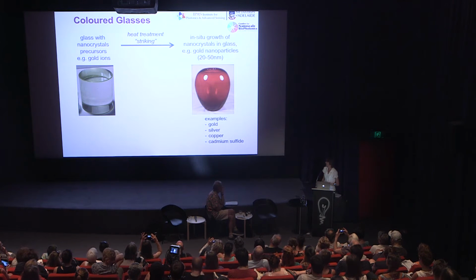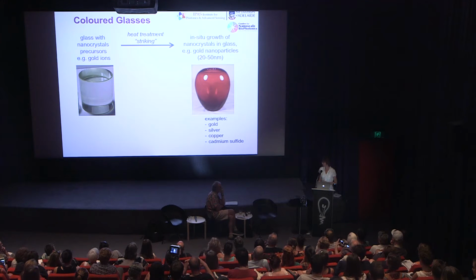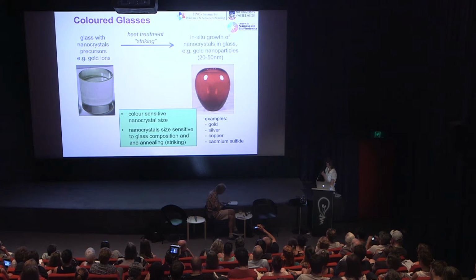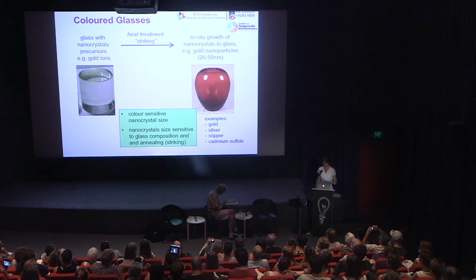And there are many other nanoparticles in glass that cause different colors. Other ingredients are silver nanoparticles, copper nanoparticles, cadmium sulfide, cadmium selenide. What really makes these colors so interesting is that the color is sensitive to the nanocrystal size. Depending on whether you have 20 nanometer or 50 nanometer nanoparticles in the glass, a different color is obtained. And which nanocrystal size is in the end formed in the glass is very sensitive to the glass composition and also to the annealing treatment. That means how the striking is done. That of course makes it very hard to control nanoparticle size and concentration.